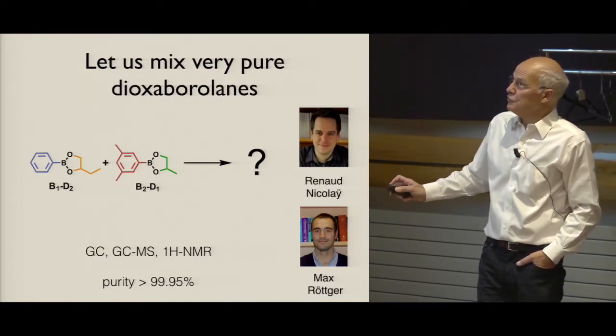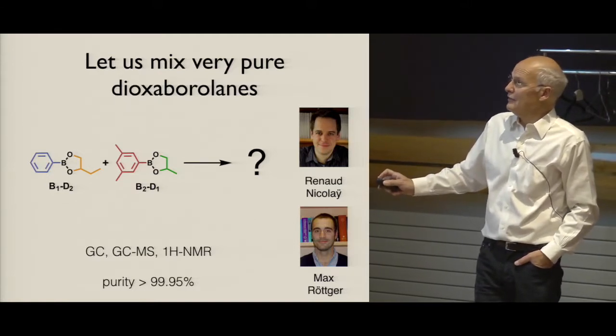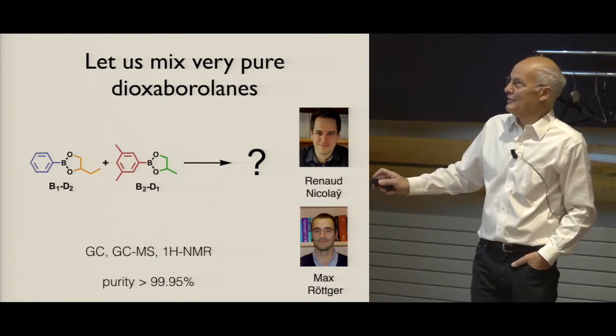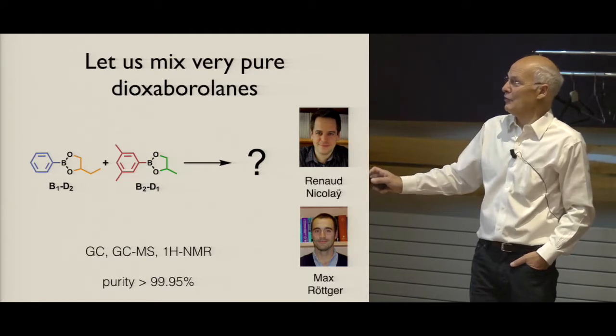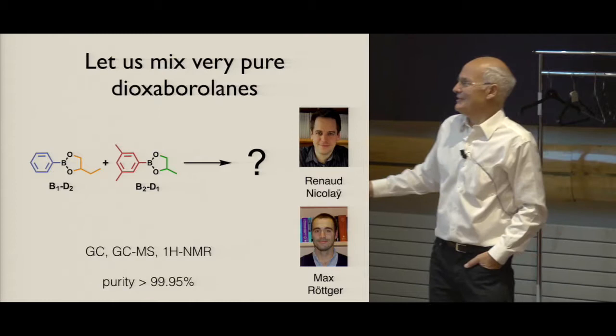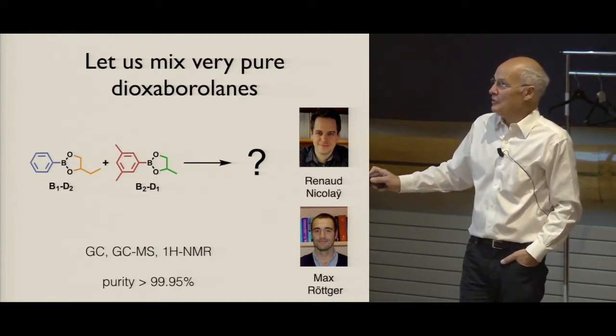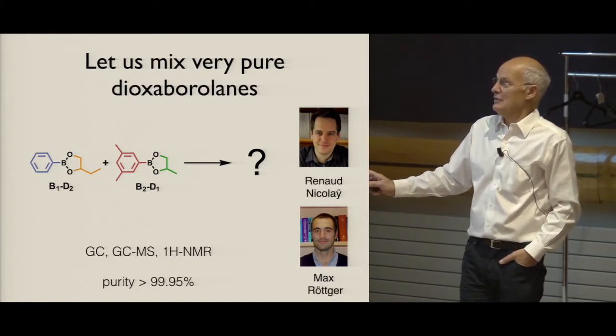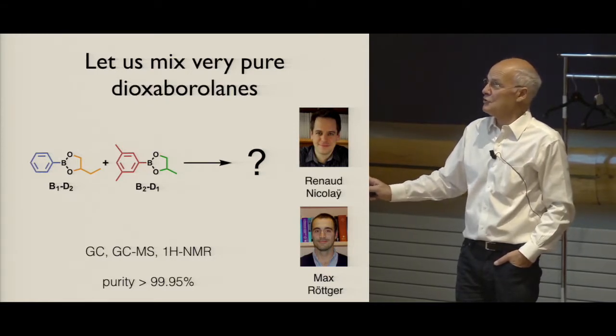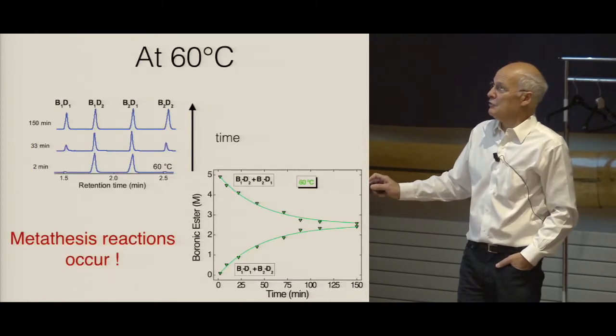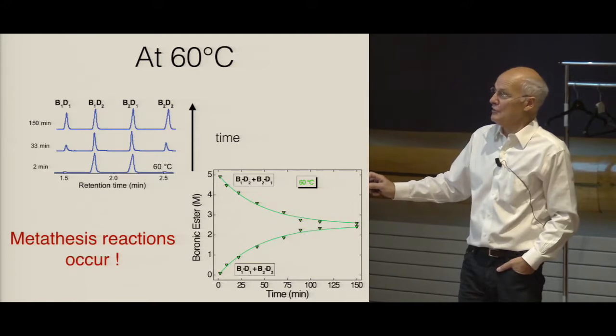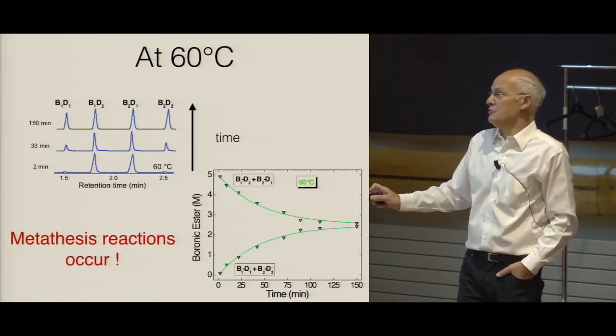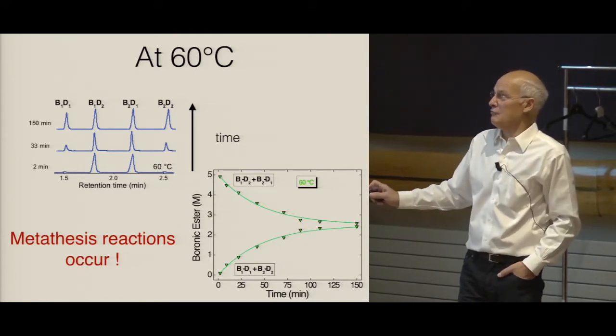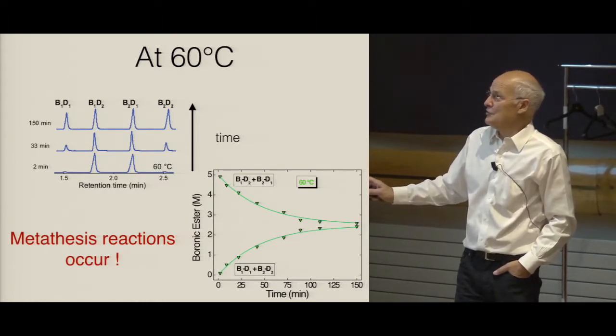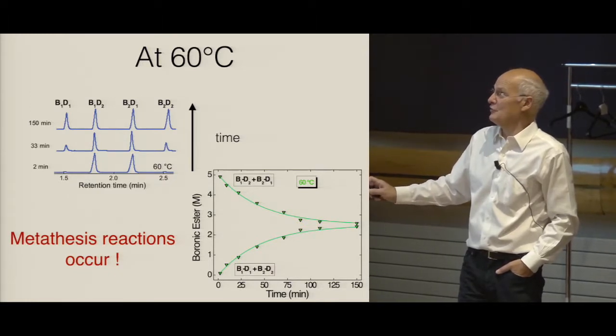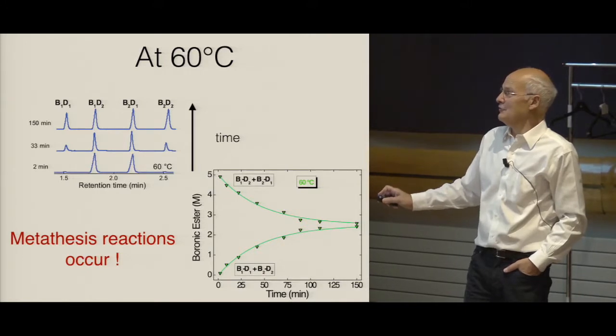And the idea here is that if we take these two boronic esters and mix them together, they will make 4 boronic esters by scrambling the acid and the diol parts without breaking apart. And so Max Röttger, who was a student with Renaud, synthesized extremely pure boronic esters. He worked in very anhydrous conditions, so as not to hydrolyze these units. And when he mixed them at 60 degrees, and he did gas chromatography and mass spectroscopy behind, it was gas chromatography, sorry. And he found that he starts with 2 esters and finishes with 4 esters, so they scrambled the diol and boron part, and the reaction is very fast.